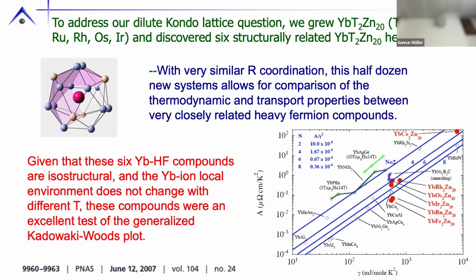All right, so to address the question about the heavy fermions, we had 6 families of rare earth T2 zinc 20, and when we got to ytterbium, it was amazing. We discovered a 6-pack of new ytterbium heavy fermions, okay? Because each of these ytterbium compounds have heavy fermion-like behavior. Here's a generalized Kadowaki-Woods plot, and I'll show you some data supporting this in a moment, where I can plot A versus gamma, and here are the 6. And what's nice is all of these are isostructural. Changing the transition metal doesn't change the CF environment of the ytterbium because nearest and next nearest neighbors are all zinc, okay, as here. So this is when I finally started believing this generalized Kadowaki-Woods, because before that, all of these different compounds are different structures, different ligands, everything.